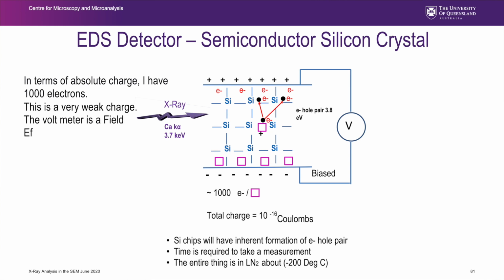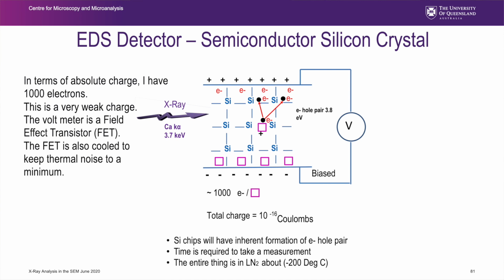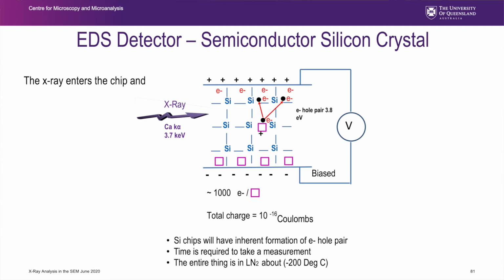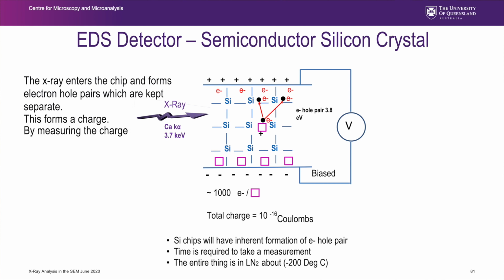So that voltmeter is a very high quality voltmeter. It's a FET, a field effect transistor. It too is typically cooled so as to keep thermal noise to a minimum. That is how an X-ray is detected. The X-ray enters the chip, forms electron hole pairs which are kept separate. That forms a charge. By measuring the charge or the voltage, I know the energy of the incoming X-ray. Very simple and elegant device.